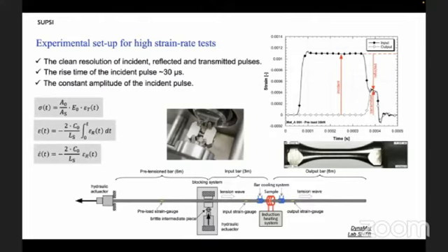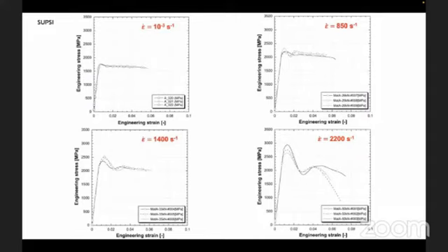In this slide, I have summarized the results at high strain rate at room temperature on smooth samples. The strain rate effects on mechanical properties of this tungsten alloy can be observed in the table shown in the slide. By depicting the engineering stress versus engineering strain, it's possible to highlight the mechanical properties. Three targets of high strain rate were set, as 850, 1400 and 2200 strain per second, obtained by imposing at room temperature 26, 35, and 50 kilonewton in the preloading bar. In fact, it's possible to observe a significant increase of the strength and strain capacity.